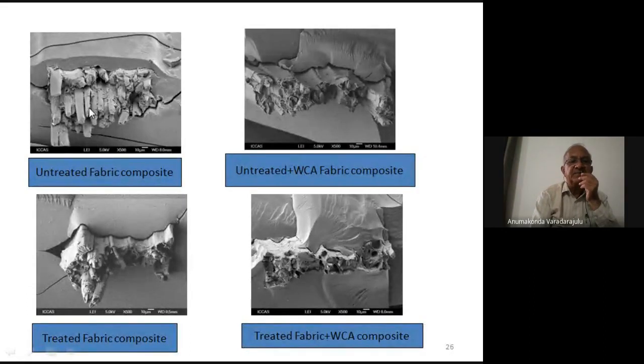Generally, whenever using the natural fabrics, it is better to remove the impurities and the hemicellulose part of it, because hemicellulose is a weak material, the surface material that can be removed by alkali treatment, that is 5% sodium hydroxide. If you dip it for about half an hour and then clean with water, that will be removed to a larger extent. So here it's not having much strength, but when we use the coupling agent, still that gap between the matrix and the fiber is there, in cross-sectional view.